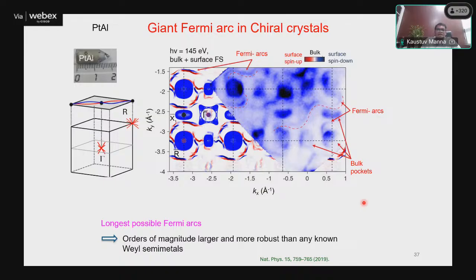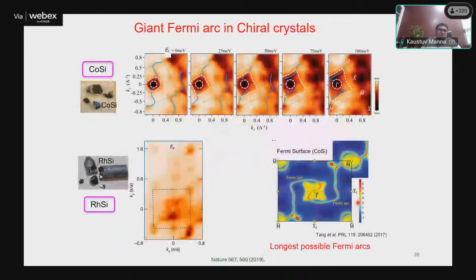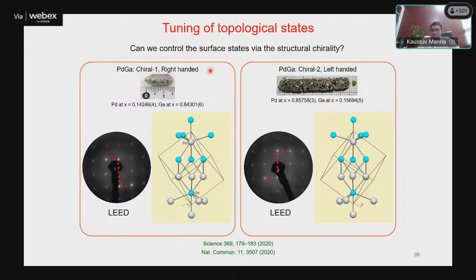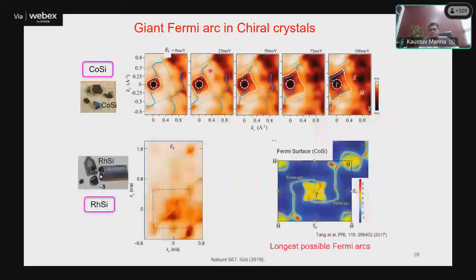However, in these compounds, platinum aluminum, cobalt silicide, rhodium silicide, we could not resolve whether the Chern number is plus 4 or minus 4. What we observe is that there is a Fermi arc connecting from the gamma point to the R point, and this is the surface state. So it matches without SOC, whatever we had, that part it matches. So that means a Chern number is present. This is the Weyl point, but whether it is 4 or 2, we do not know. For that, what we had to do next, okay, Chern number 4, I'll come.